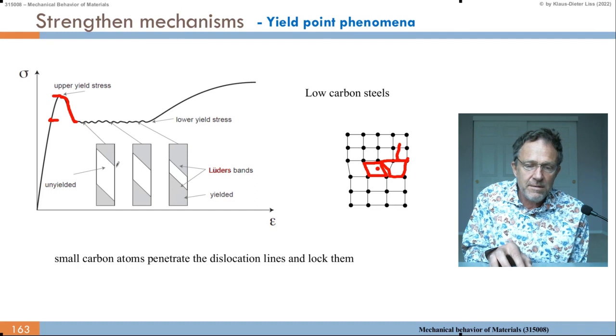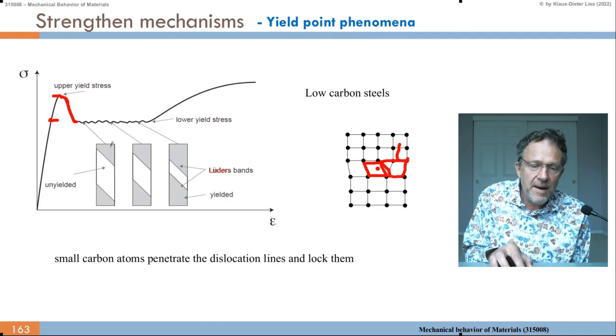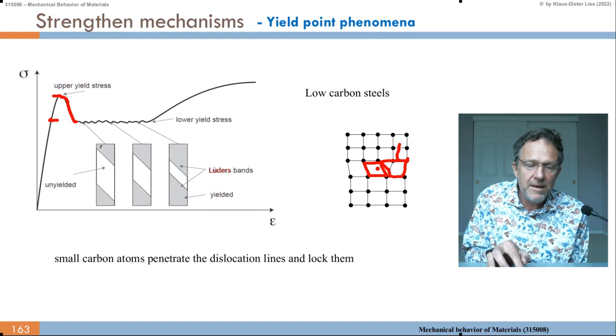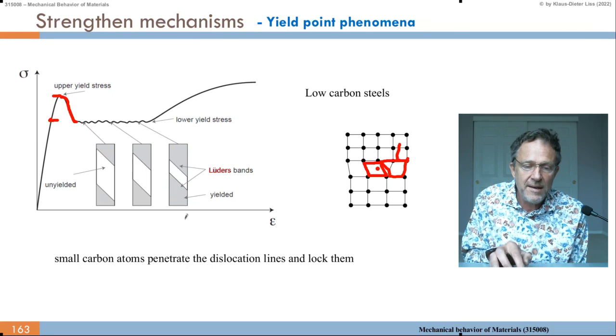And that can happen by an area which is unyielded and which is yielded. So eventually I have here the unyielded material in white and I have the yielded material in gray. But then we know as we yield and as we propagate epsilon, the extension, we get work hardening in the gray area. So if work hardening becomes higher than moving away from the carbon, then I move this front inside. And here also move the front inside and inside.